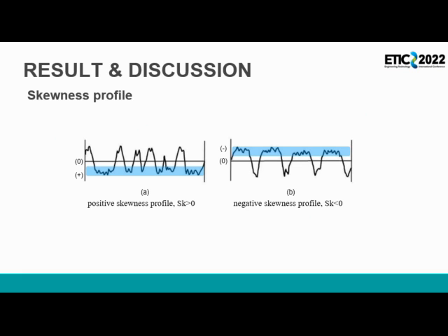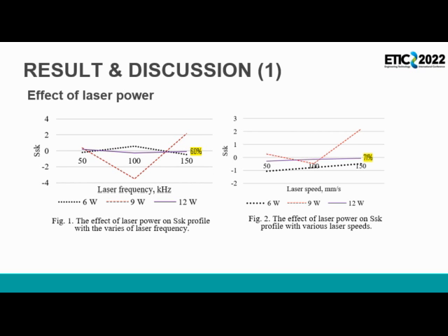As illustrated in the figure above, a negative value of skewness implies that the ground surface features a prevalence of round peaks and sharp valleys. When it comes to the turned surface, a positive value of skewness indicates that there are relatively more pointed peaks and round valleys. The goal is to achieve mirror-like surface properties as discussed in the literature.